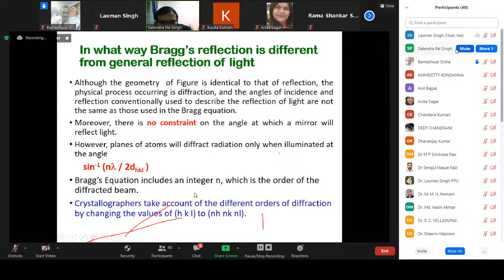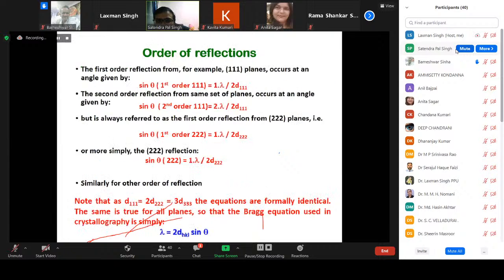So the other parameter in the Bragg equation is the order of the reflections, which we should understand. Now, if we talk of the first order reflection, for example from the 1, 1, 1 plane, it occurs at the angle theta where sin theta equals n lambda over 2d. Instead of d, we say d HKL, so d 1, 1, 1.